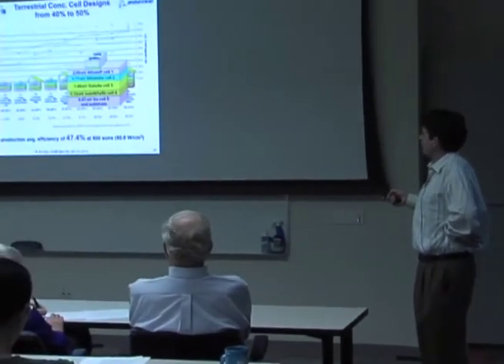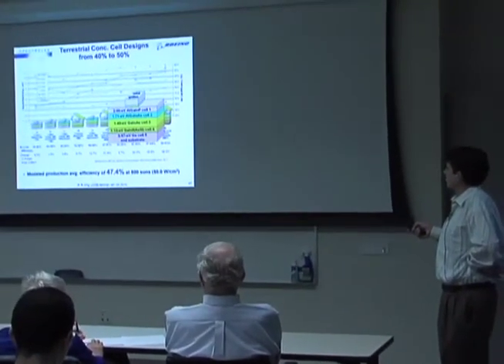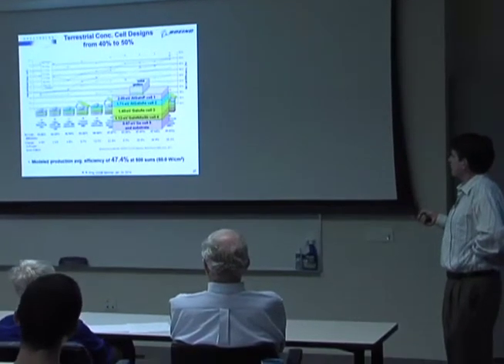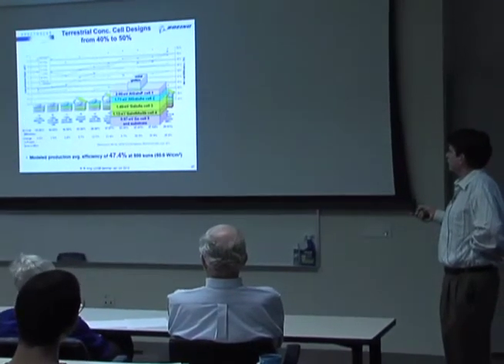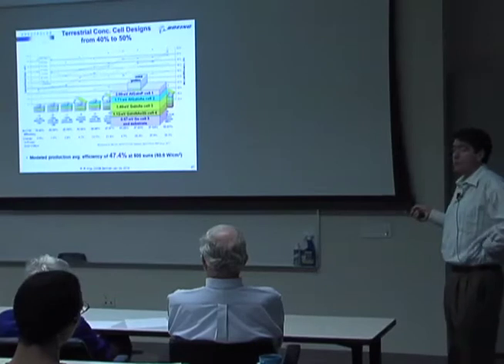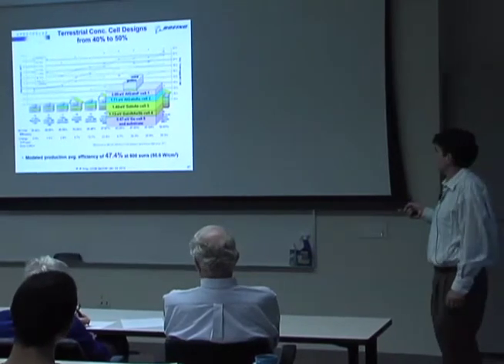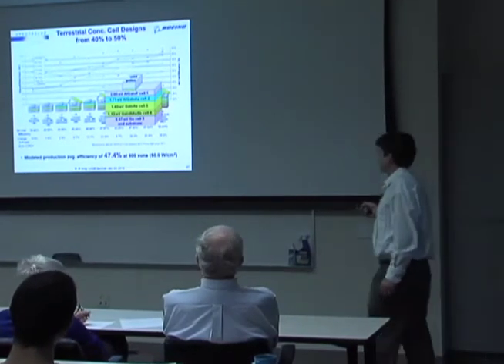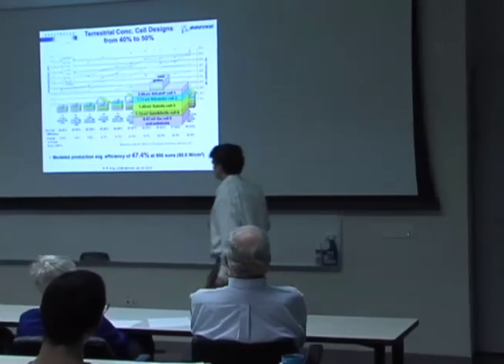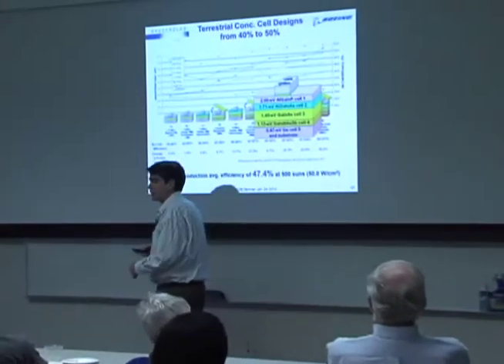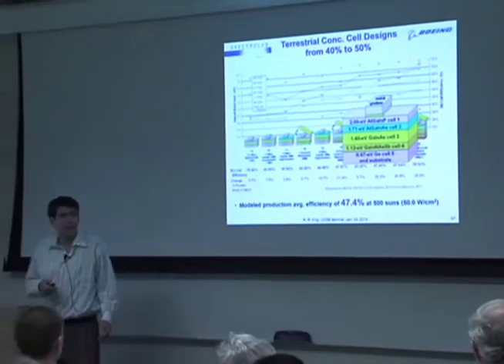We can keep the lattice constant the same, and yet both of those drive the band gap down. So we can use the gallium indium nitride arsenide in a multijunction cell in this way. There's a real scarcity of appropriate semiconductor materials with this 1 eV band gap at the gallium arsenide lattice constant, which this gallium indium nitride arsenide fills.